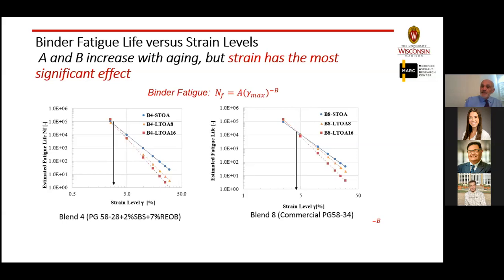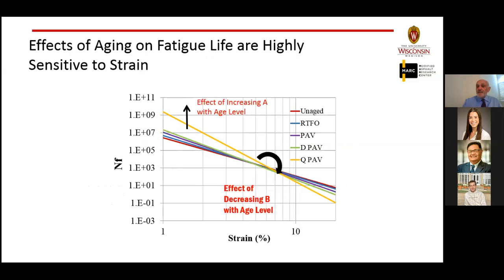Your university was the first to focus on the post-peak slope and looking at what happens when the cracks start propagating. In a very successful way, you could actually link it to the field. Similar to what we're seeing here, your data can actually confirm what we need to do, which is looking at the higher strain levels. So the behavior in fatigue, and some of these reports that you can see, they put the mix or the binder in aging, they took it out, retested it, and it became stronger.